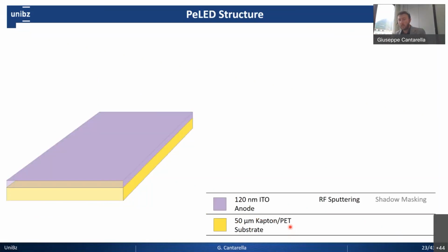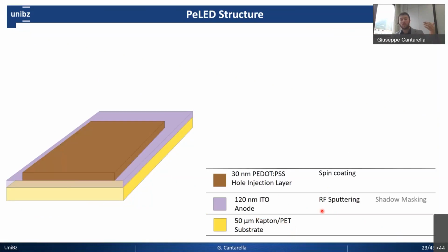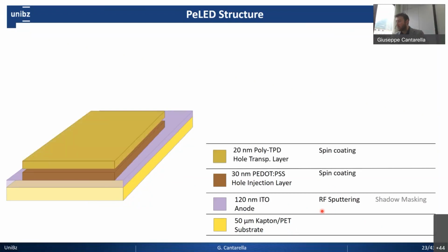Then we proceed with the deposition of 120 nanometer of indium tin oxide as a transparent conductor. This was sputtered by radio frequency sputtering at room temperature. Then the LED fabrication starts. We first spin coat as hole injection layer 30 nanometer of PEDOT:PSS. Then we have as hole transport layer 20 nanometer of poly-TPD.